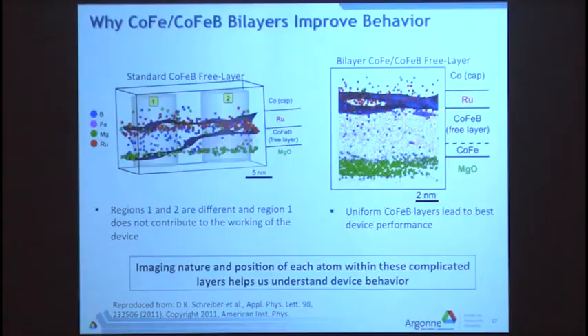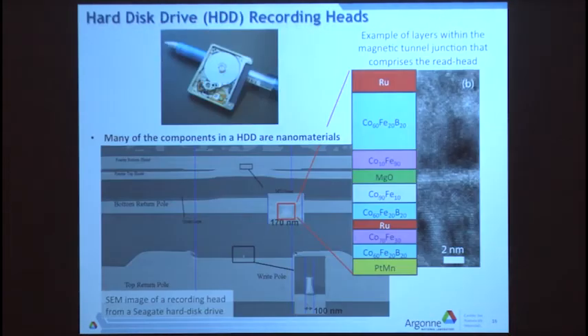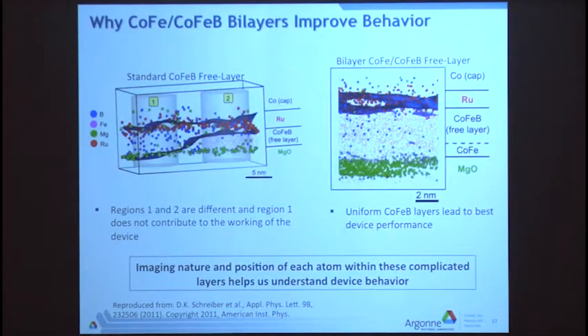So we went in, in my research group, with something called atom probe tomography, which allows us in 3 dimensions to map out where the atoms are in the material. I do apologize, I forgot to give you one rather vital piece of information, which is that what we're going to concentrate on is these 2 layers up here. If we replace those 2 layers by 1 layer, which was the original old structure, and concentrate on the boron atoms, you can see here there are lots of boron atoms, and in here there are not very many boron atoms.